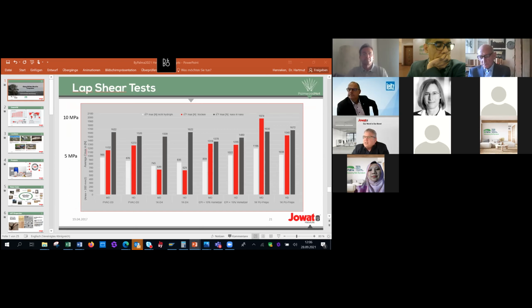In white is the standard with no pre-treatment. In red, we did a pre-treatment, dried the samples, and then did the adhesive application and the gluing. And in black, it is pre-treatment and immediate, so wet in wet, immediate bonding. And then after 1 week, final strength of the material, 1 week in the climate chamber at 25 degrees, we did the measurements. And you can see that dispersions, never mind if it's a 1K, a D4 dispersion or D3 dispersion, they're always in the range, also EPI, always in the range of 800 to 1000 Newton, which is with the area about 5 megapascal.